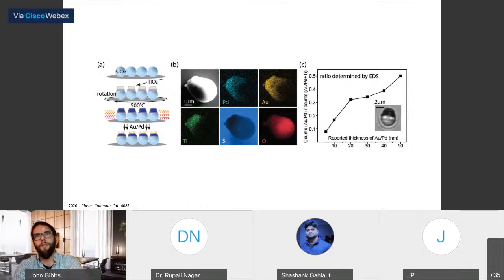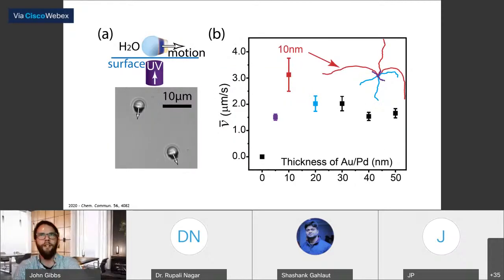Something interesting about the results is that we found there's an optimized amount of material that seems to enhance the catalytic behavior the most, which we found to be about 10 nanometers. What we think is happening is that once you deposit enough gold, you end up completely covering up the surface, so you're no longer exposing as much TiO2. We think that's where we find this convergence to about 2 micrometers per second, once we get a thickness thick enough that you have a more or less continuous film.